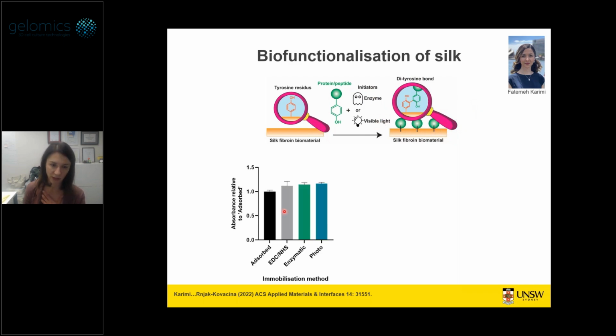And we've shown that with an example by immobilizing perlecan, which is a vascular basement membrane proteoglycan, where this is perlecan adsorbed, passively adsorbed on the silk materials, cross-linked, immobilized via EDC and NHS chemistry, which is a very common chemistry used for silk, or enzymatic or photoinitiated dityrosine cross-linking. And so you can see that we get similar amounts.